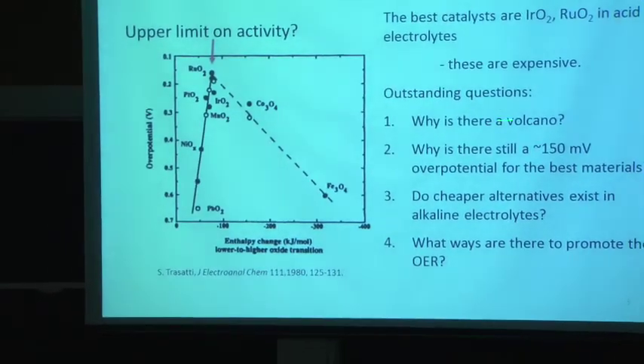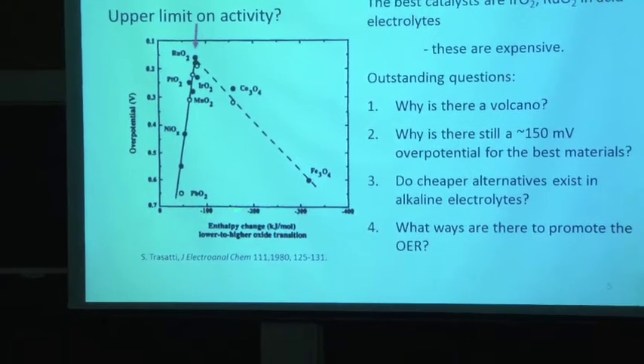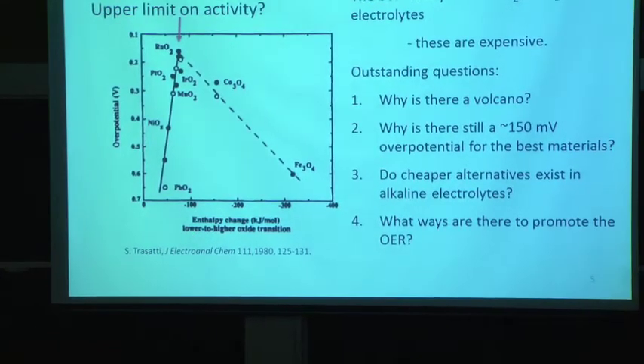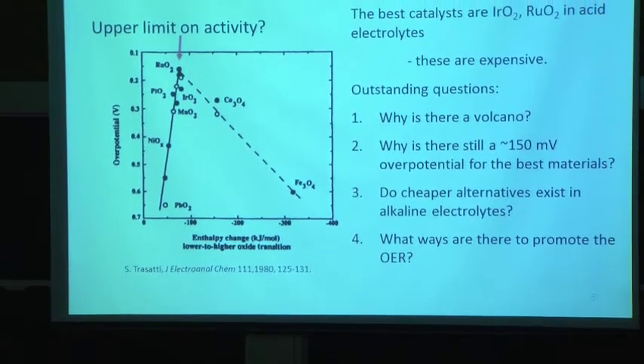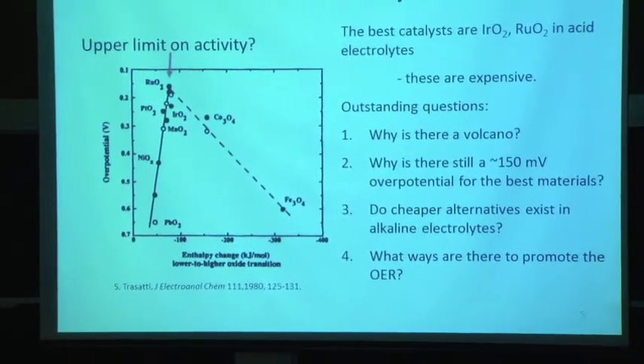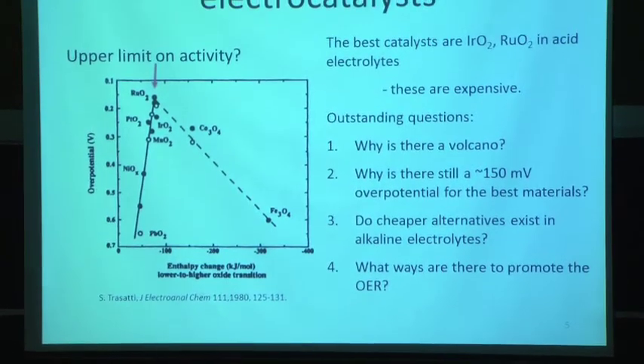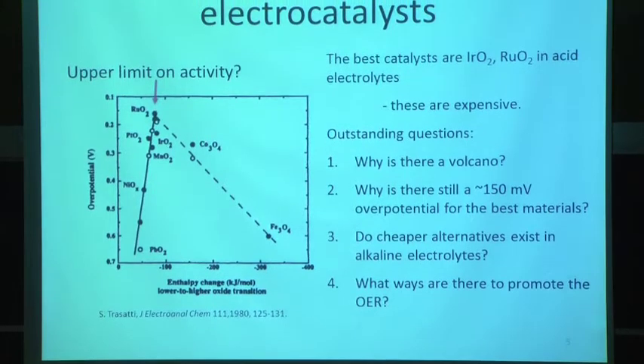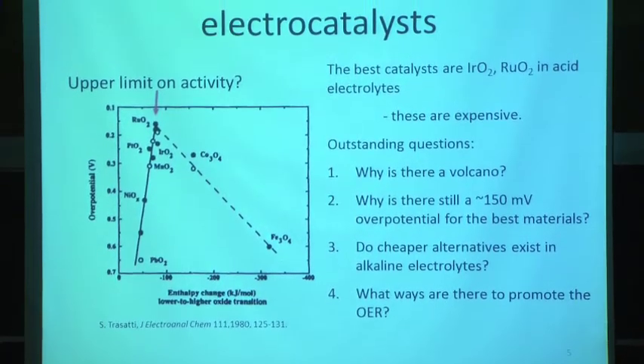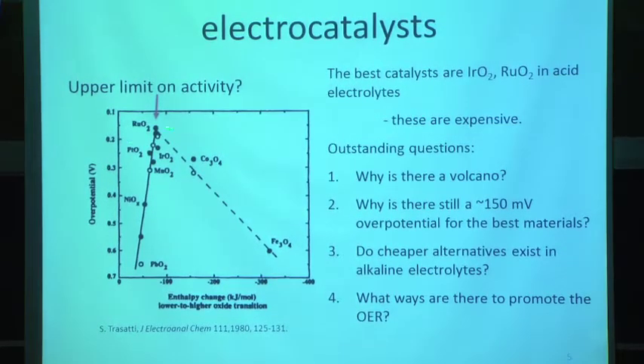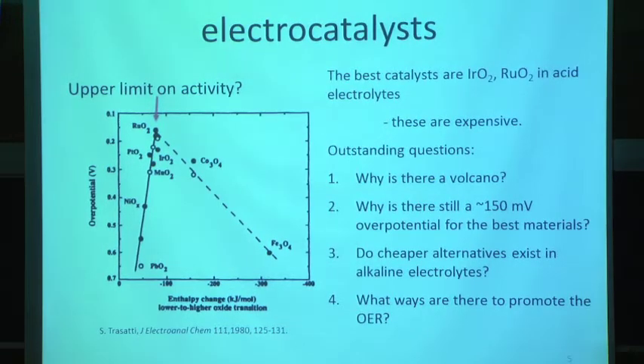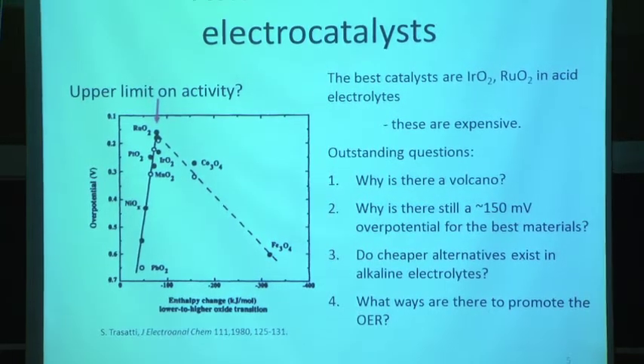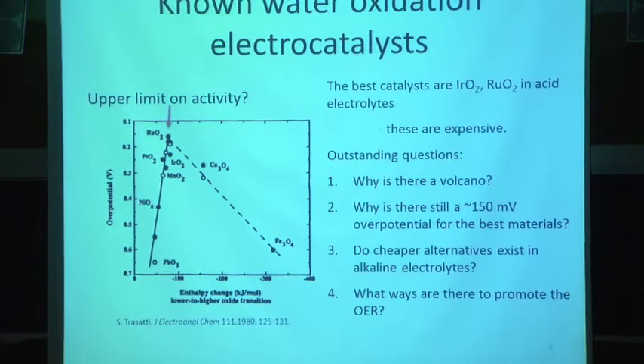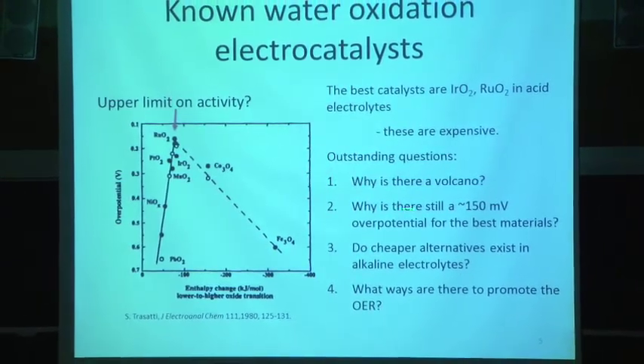One is, why do we see this volcano? That is, this here is an enthalpy change for lower to higher oxide transition. It's the energy required to oxidize or reduce the metal oxide. If you like, that's related to the strength of an oxygen bond coming off the surface. So why does the activity go up and then down? Why is there still sort of a 150, 200 millivolt overpotential? Why haven't people found good catalysts that are very active at much lower overpotentials? So we'll talk about that.